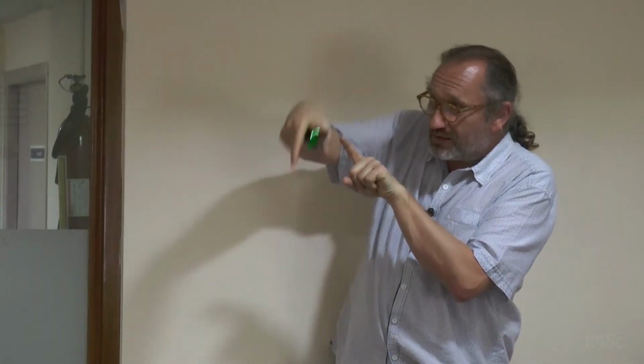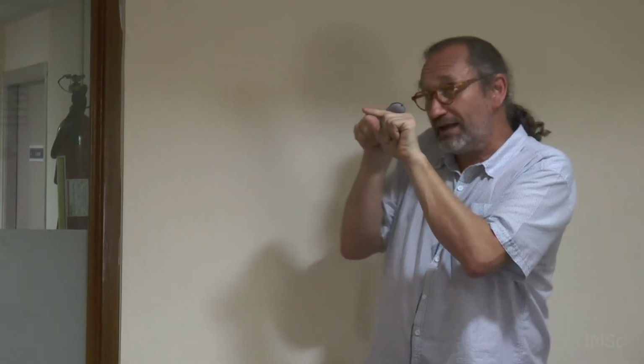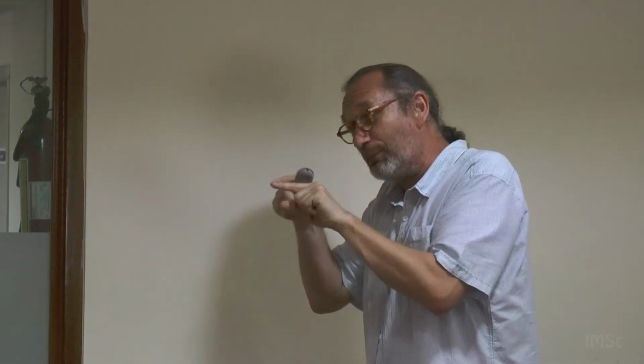What happens is that there is some mobility, not very much, but some. When the front advances, it rearranges a few of the disorder. And where is it put? This disorder moves to the place where it will minimize the energy dissipation. So somehow the system is trying to optimize the jumps it's doing, to do things more easily without going to very high barriers. It's looking for paths in the free energy, and if I can just kick a little bit the stone to have a lower path, I do it, and then I pass. By this, it's optimizing. But you need some disorder, and when you heat up and erase all the disorder, you erase the learning process, and the system has to start to learn again.